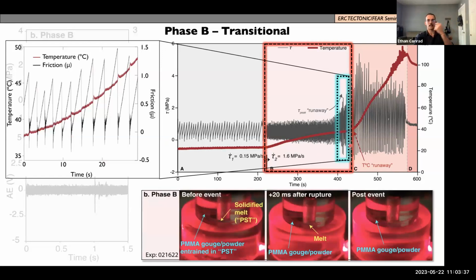And we see that here from the transition point, kind of the end of this phase, the exponential increase in temperature because you're building and you have these very rapid events without enough time for heat to dissipate. And in these frames that we have below, we see that we're starting to form melt in this semi-opaque color, and there's some PMMA gouge or powder sort of entrained in this melt and then later cooled in this melt. But because of the melting, and the starting of bonding the interface, each event gets bigger, and thus you release more energy in each event. You have more melting and more bonding, and the temperature continues to go up. And this is what we're calling this kind of temperature and shear stress runaway, where everything very rapidly increases and becomes very large events because of this welding effect.